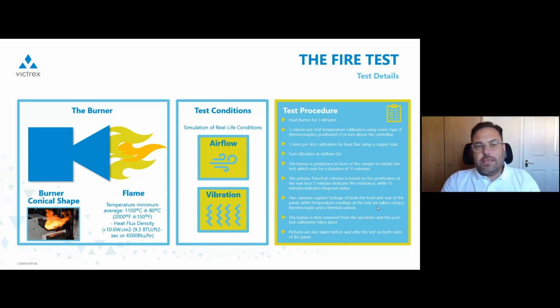The duration of the test is 15 minutes minimum. The pass-fail criterion for this test is simple. If the fire penetrates, if the fire goes through, and you have secondary or back ignition of the back face, this means that you have failed the test. So there are two important times for this test. The first one is 5 minutes. If nothing happens at 5 minutes and there is no fire penetration, you can then call your material fire resistant. Then if 10 more minutes elapse, coming up to a total of 15 minutes, then your material is fireproof, assuming again no fire penetration.